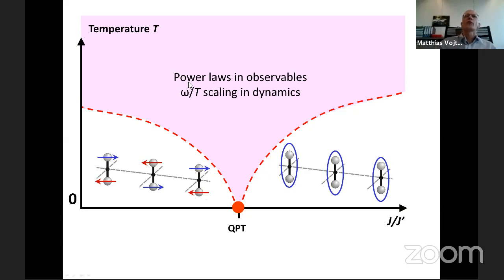For instance, there are non-trivial power laws in observables like specific heat or susceptibility, power laws as function of temperature. And dynamical observables typically obey scaling laws, for instance, omega over T scaling. And all these are characteristics which are unique to this quantum critical regime and do not occur in any of the stable phases. So do not occur in the left and the right, but only in this colored regime up here. Now, this is something which can be accessed experimentally.